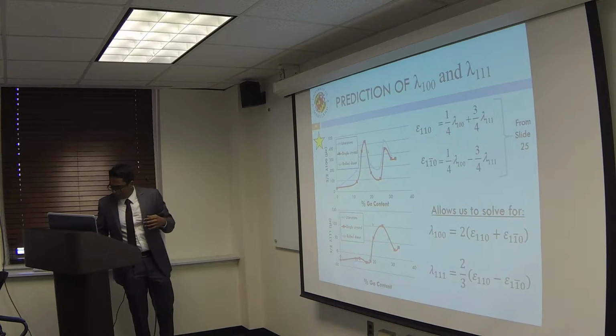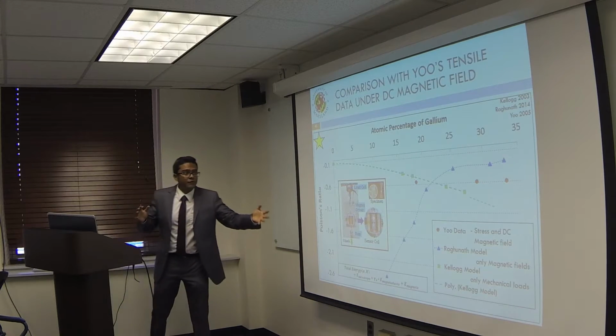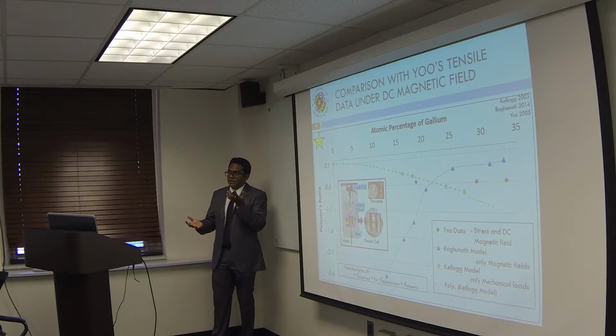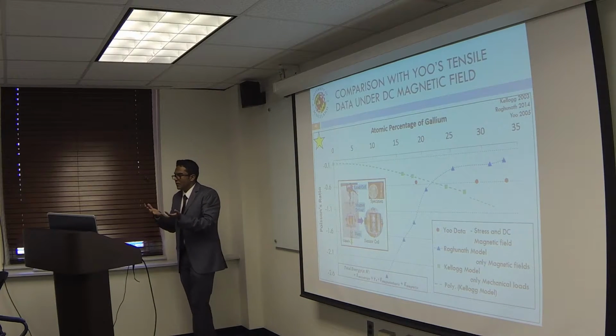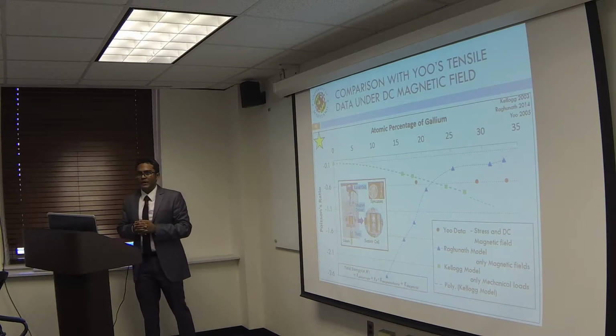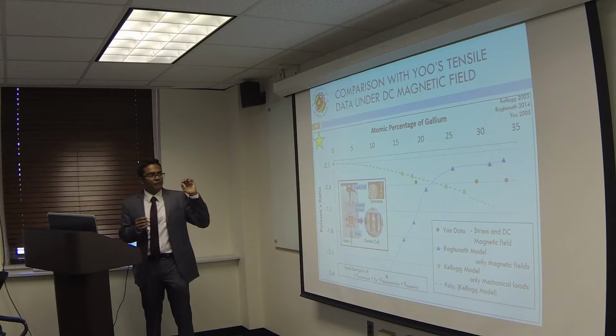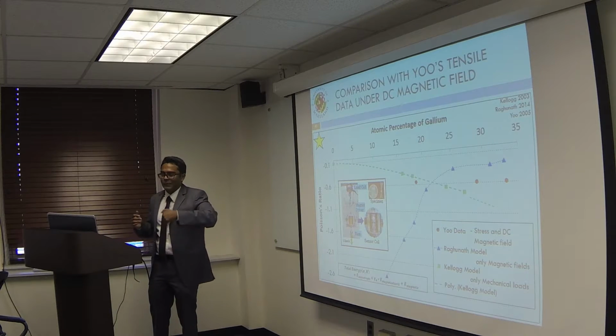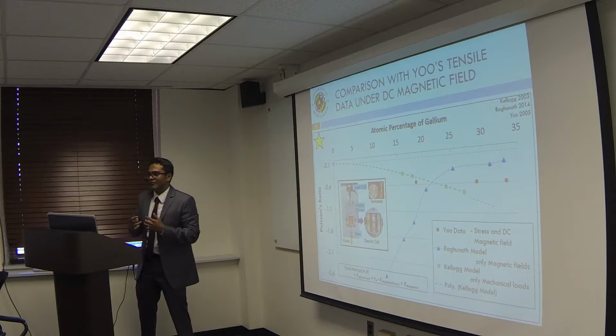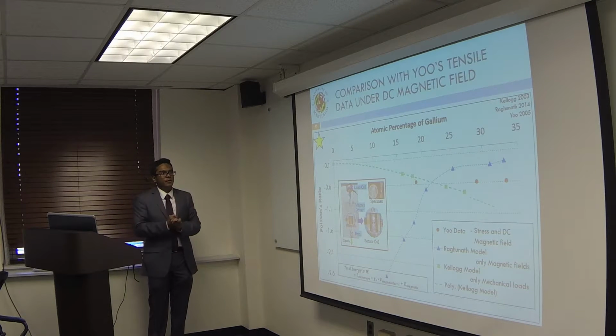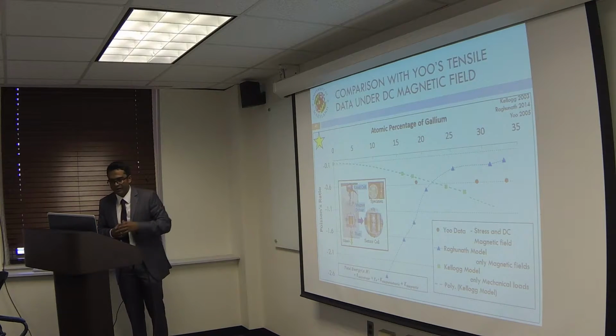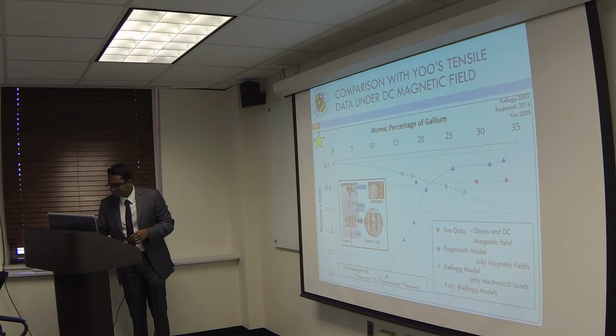So this kind of confirms the fact that the magnetic energy and the mechanical energy are competing with one another in the magnetoelastic system. If one is leading to lattice restriction, the other one is leading to lattice softening, and that is the reason why Dr. Yu's data falls right in between mine and Rick Kellogg's.